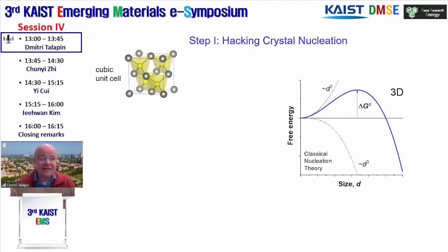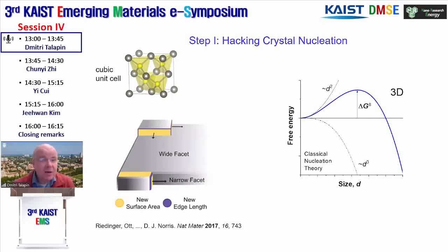And there was a lot of work along these lines accomplished by the community. Now, if we want to bring it to the next level, we need to understand and improve control for both steps. First, nucleation. Let's consider classical nucleation theory. The idea is that in order to nucleate, the system must climb the nucleation, activation barriers, and grow to the size of the critical nucleus. At least in the classical realization of this approach, the idea was that the nucleus forms uniform or nearly spherical, or as close to spherical as possible.